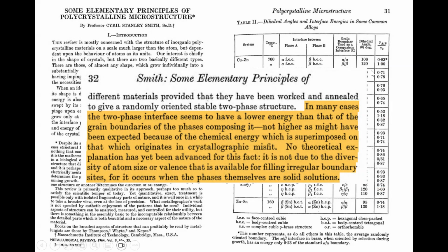So he says, in many cases, the two-phase interface seems to have a lower energy than that of the grain boundaries of the phases that are composing it, not higher, as perhaps might have been expected. And what's amusing is that there is no theoretical explanation yet advanced for this fact. He hasn't got a clue why this should be. That is still the case. No one has a clue why it should be.